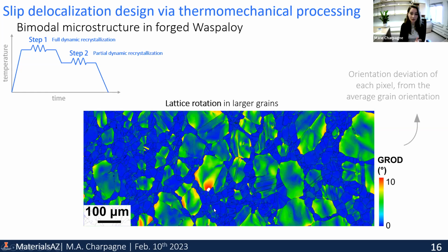On the other hand, you see that the smaller grains that were formed during step 2 are much smaller and also more stress-free, if I may say, given that they're pure blue here. They have a more consistent orientation throughout, and they are not subject to very high rotations. The reason why we applied step 2, I just want to comment on this, is to increase the strength. Because if you have a microstructure that has very large grains, the strength goes down. So the second round is there to crank up the strength of this material.